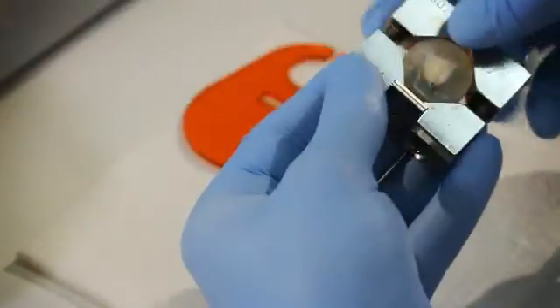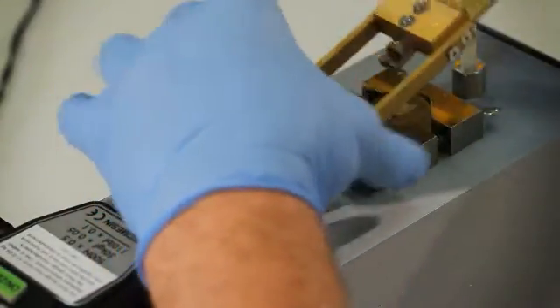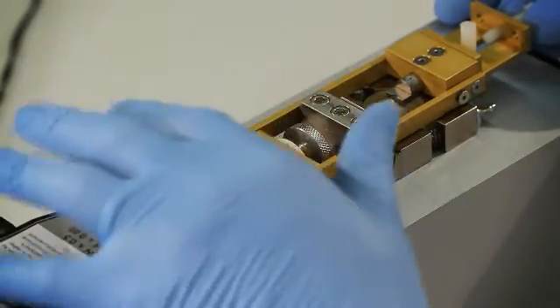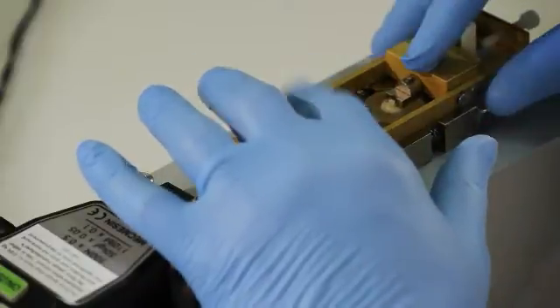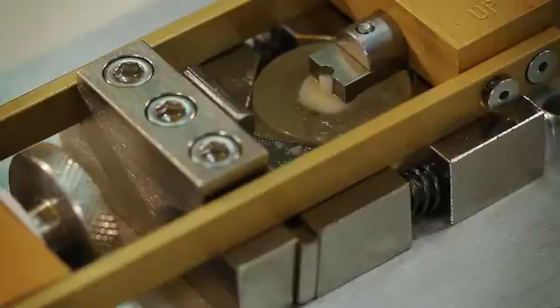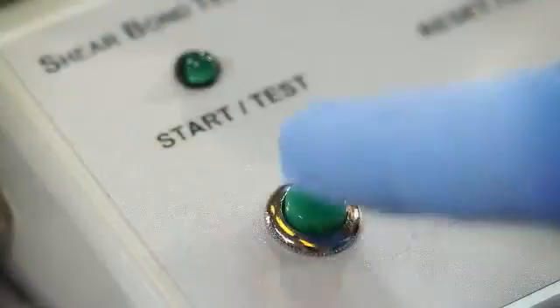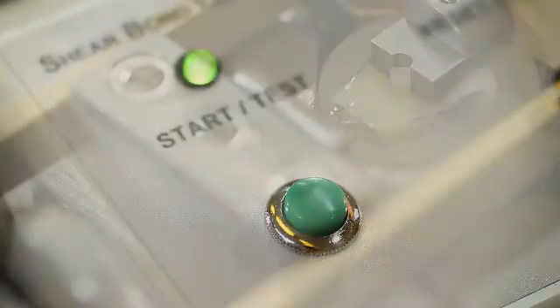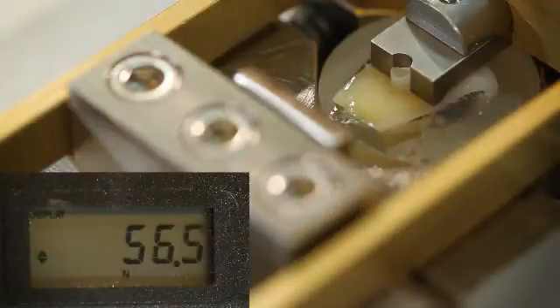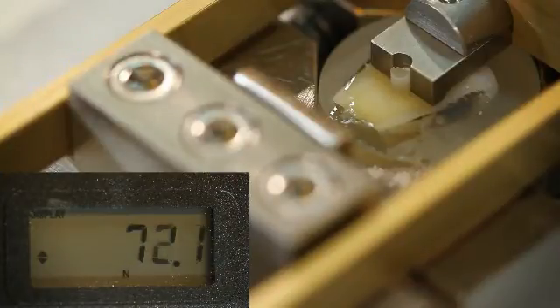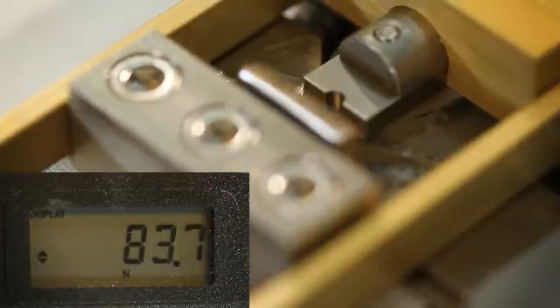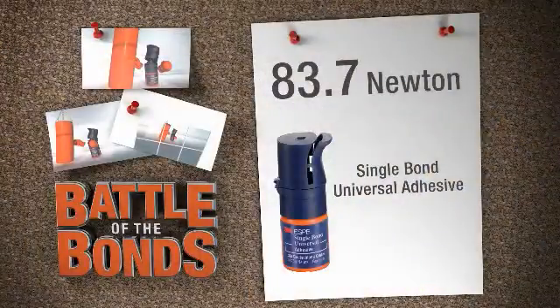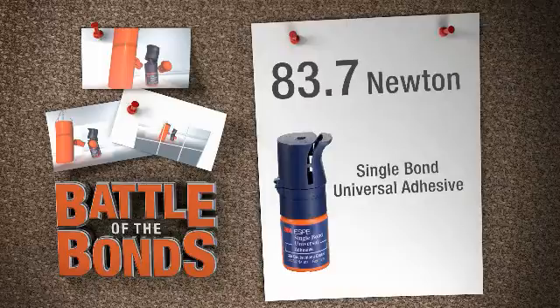Each sample was placed in a clamp and loaded into the portable shear bond strength testing unit. The wheel was slowly turned, bringing the shearing mechanism into contact with the composite. Once the Start Test button was pressed, the shearing force against the composite was gradually increased until the composite debonded. The force required to break or debond the samples was recorded in newtons on the electronic gauge. In this example, 83.7 Newton was the force needed to debond the composite using Single Bond Universal Adhesive.